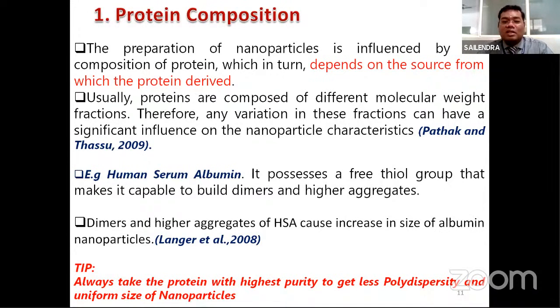Now your protein is not that pure, and you are following a protocol which utilizes a protein which is 99% pure, and you are using an impure protein. Definitely you're not going to get 100 to 200 nanometer particle size. Definitely the particle size is going to shoot up: 500 nanometers, 1 micrometer, go up to 2 micrometers, it can go up to 10 micrometers also.